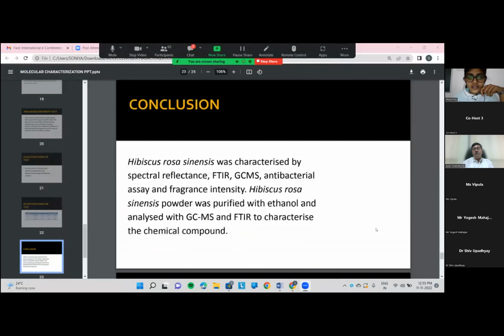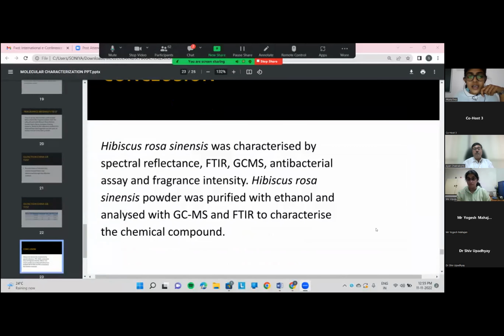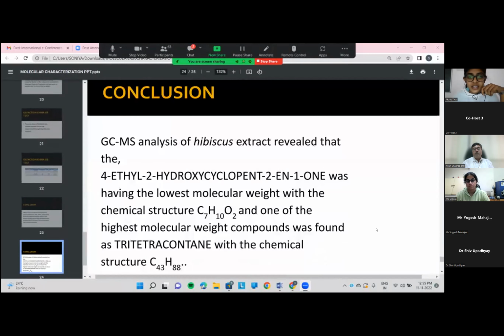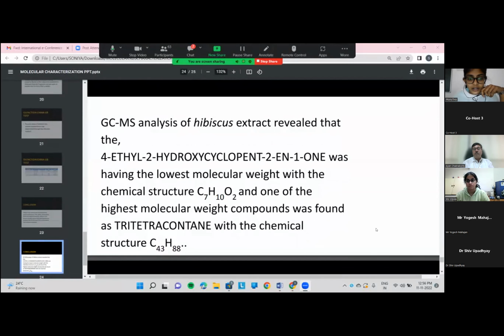Conclusion. Hibiscus rosa-sinensis was characterized by spectral reflectance, FTIR, GCMS, antibacterial assay, and fragrance intensity. Hibiscus rosa-sinensis powder was purified with ethanol and analyzed with GCMS and FTIR to characterize the chemical compounds. GCMS analysis of the hibiscus extract revealed that 4-ethyl-2-hydroxycyclopent-2-en-1-one had the lowest molecular weight, with the chemical formula C7H10O2, and one of the highest molecular weight compounds was found to be tritetracontane, with the chemical formula C43H88. These are the references I used for the presentation, sir.